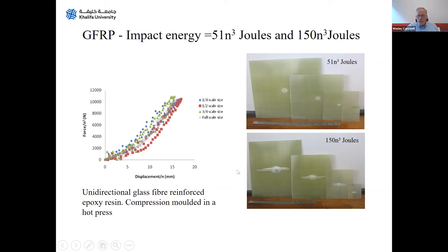So if we look at the higher impact energy, 150 N cubed joules, is perhaps easier to see. You can see the largest sample here. We've got this delamination. You've got some sort of spalling as well as the rear surface fibers. And you see similar sort of damage levels across the four scale sizes as well. So we're getting very similar damage patterns in the quarter scale sample as we do in what we term our full scale sample as well.